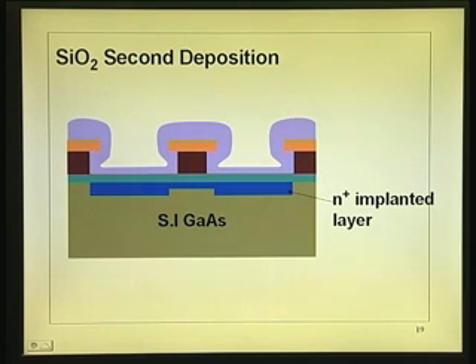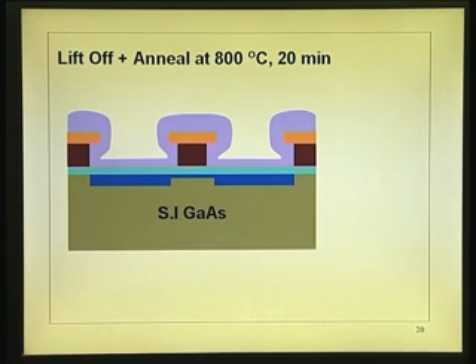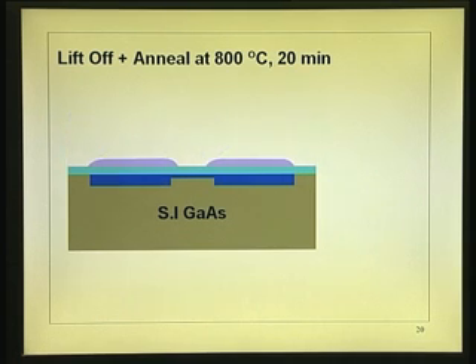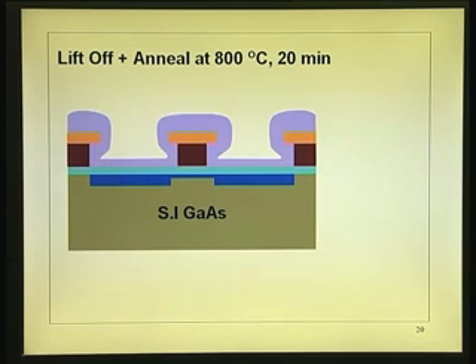That is how it comes. See, I deposit everywhere, it is conformal deposition, so it takes the shape of that. That is the oxide that you deposit. Now, the key thing here is that is second SiO2 layer. Key thing is I just put it in a solution which dissolves the photoresist. Okay? This is the photoresist, this is SiO2. I put it in a solution which will dissolve that. What will happen? Whatever is above that will go, that is lift off. See, whatever was there over this region, it is dissolved now in acetone. Whatever is above that, including that oxide, goes off.